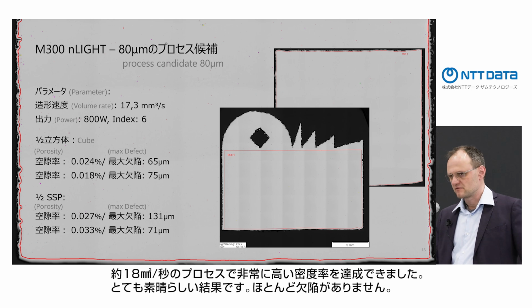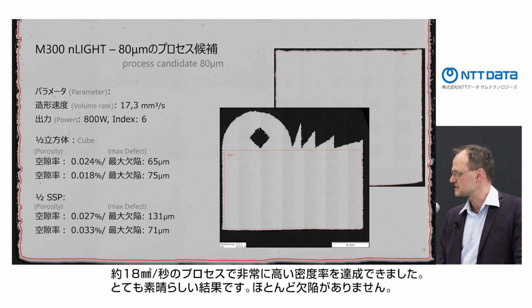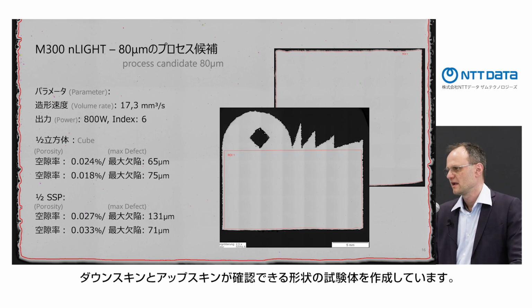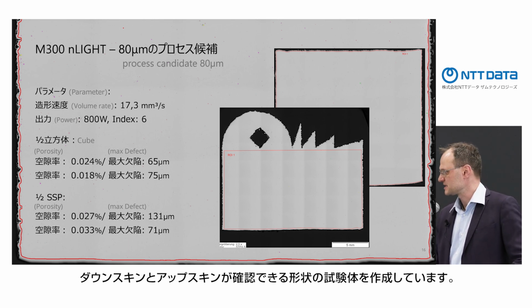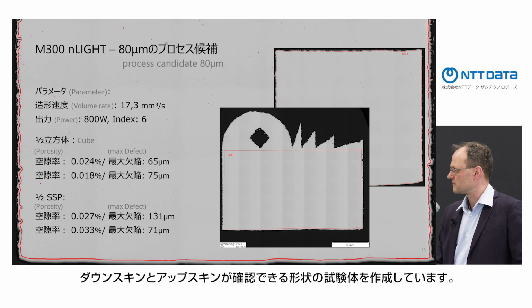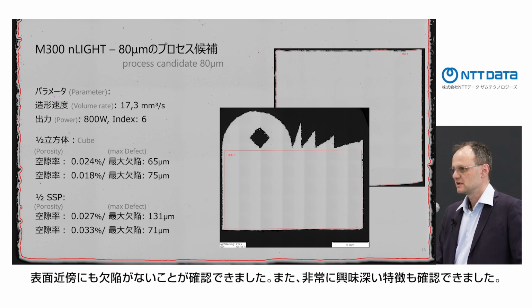For these roughly 18 cubic millimeter per second processes, what we were able to achieve is extremely high density. So the density is very excellent. It's nearly pore-free, also in samples that we are generating, which we call parts, with downskin areas or upskin areas. So we see that not even underneath the surface is there porosity.